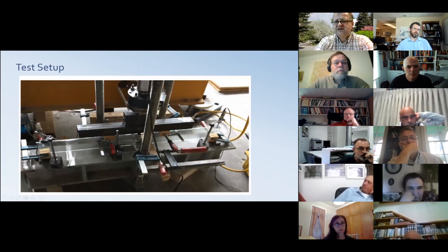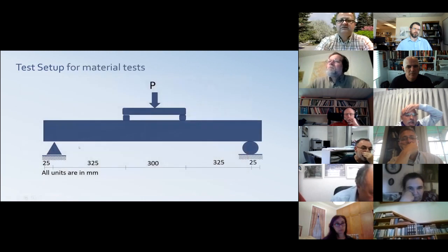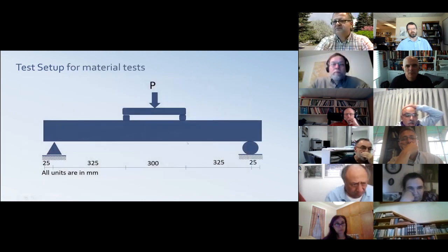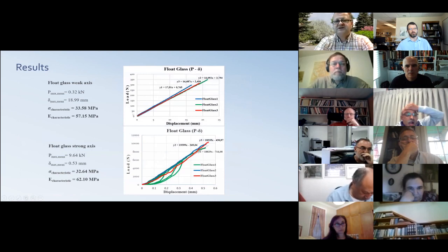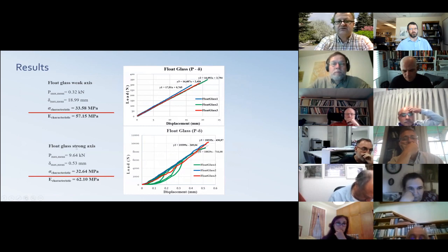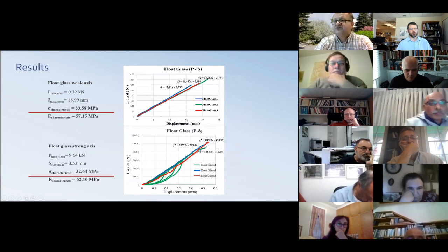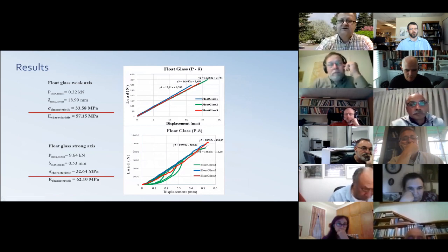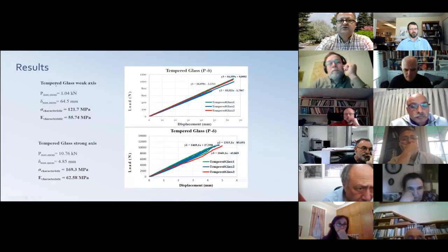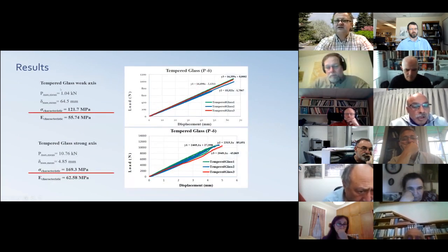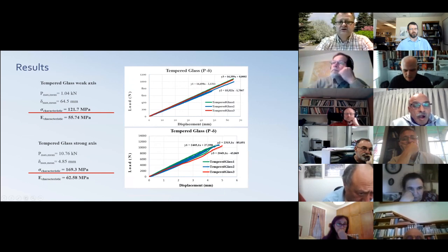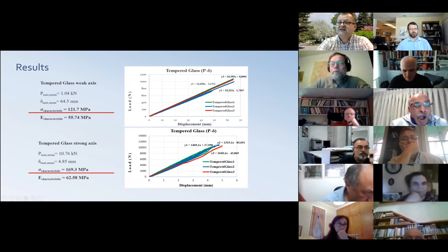So we tested glass in strong axis and then weak axis, and we applied a simple bending test, and we got the results. So regular glass had a bending strength of 33, 34 megapascal, which is as strong as concrete, by the way. This is regular plain glass. When you use tempered glass, which is heat treated, it goes to a large 170 megapascal in tension for glass, which is very high.